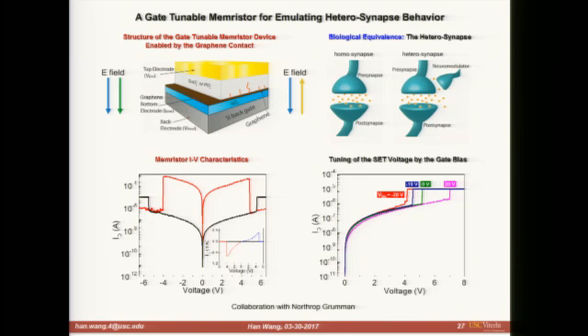The good thing about graphene is that because it's extremely thin—this is single-layer graphene—we can also build a gate underneath. The gate electric field can penetrate through the graphene layer and influence the whole filament formation process in the median layer.